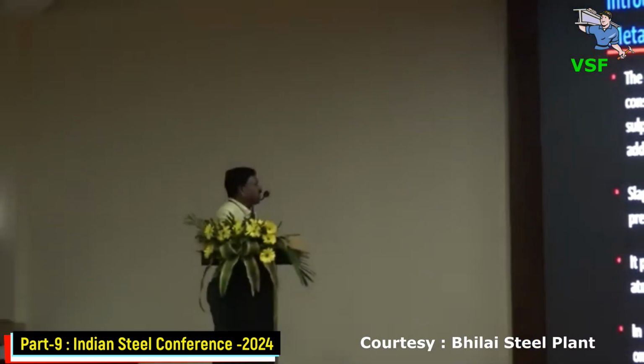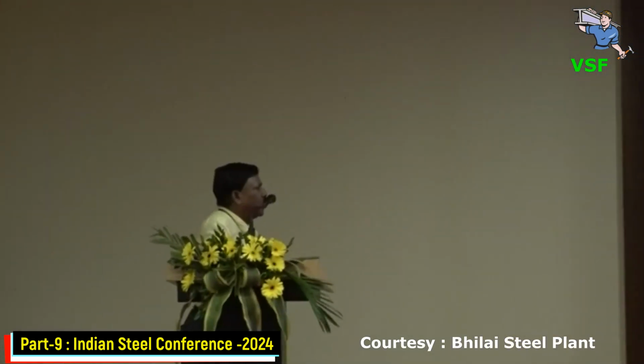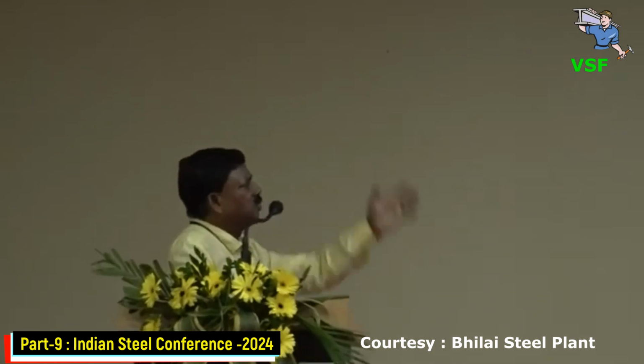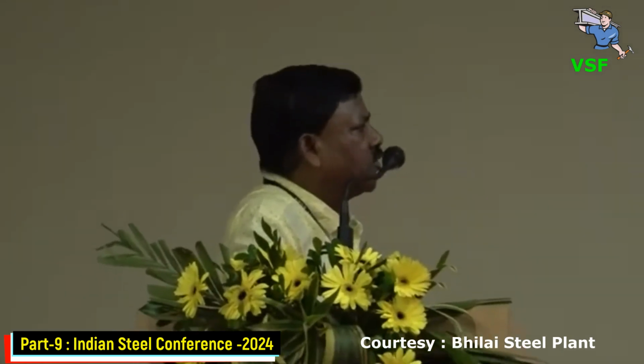We have done some study on slag, because basically it is about monitoring the slag. The slag should have the following properties: low melting point, low viscosity, low surface tension. We have done some phase diagram study, and in this phase diagram, we found that if you can produce tricalcium and dicalcium silicate, the melting point is 1990 to 2030. The calcium ferrite is 1216, and fluorspar, which we add for fluidity, is 1340. So we have to avoid all these things. For the converter, we need magnesium oxide. Those are the phases we have to get so that you get better life.